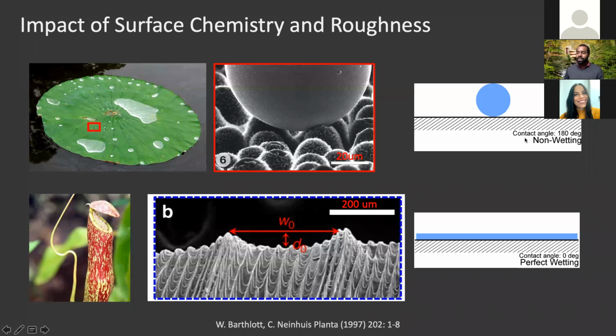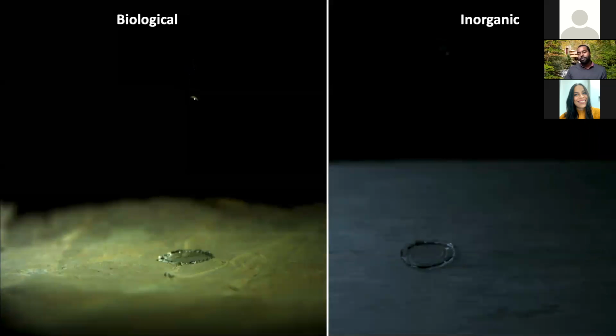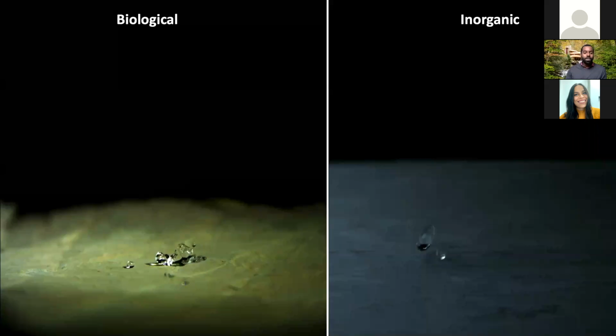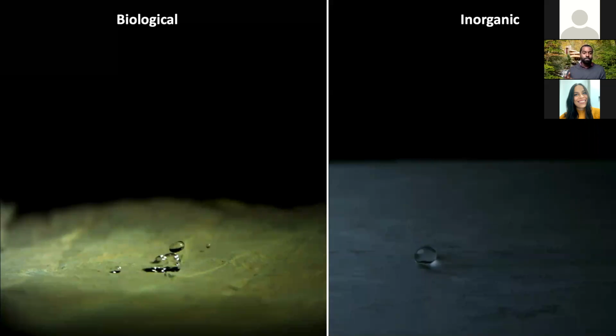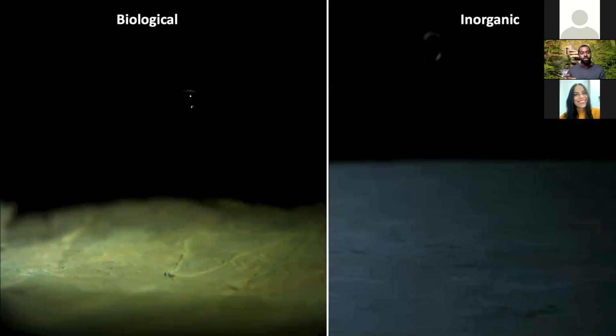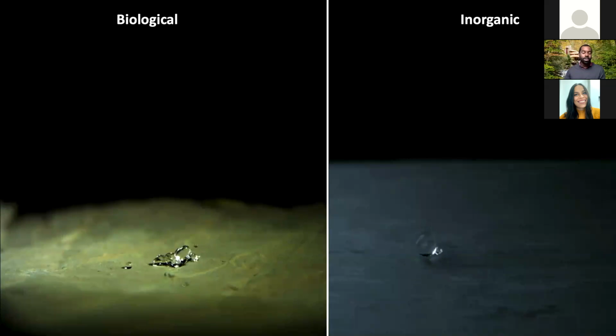And in practice, on the left, we have biological systems, and on the right, we have an inorganic system we made out of titanium. Just talking about super hydrophobic and being able to prevent water from sticking, we're able to do that through the nano and microstructuring with the proper surface chemistry. We can see that in the biological case, there's a little bit more sticking. It's not as perfect as our inorganic case. With the inorganic case, we have nearly complete repulsion, and we're working with a material that's more robust than what you find in natural systems. We're working with titanium.